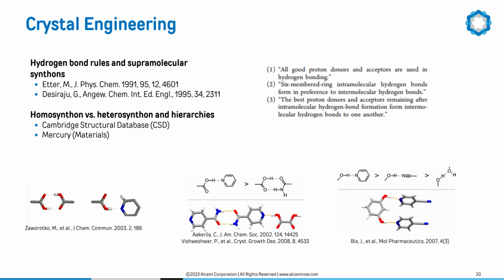Extensive studies within the field led to the generation of synthon hierarchies. Two categories of supramolecular synthons were defined: homosynthons and heterosynthons. Homosynthons are composed of self-complementary functional groups such as carboxylic acid homodimer. Heterosynthons are composed of different but complementary functional groups, as exemplified by acid pyridine heterodimer. It was found that in co-crystals the formation of heterosynthons is generally favored over homosynthons.